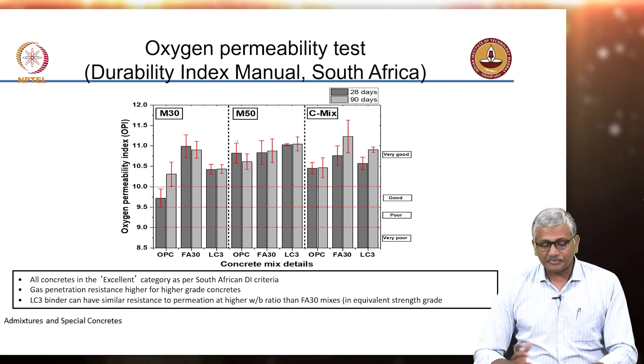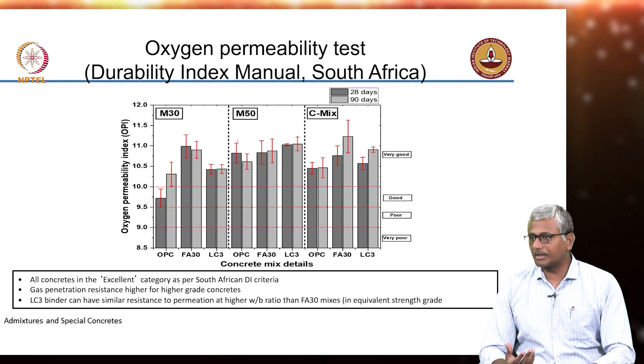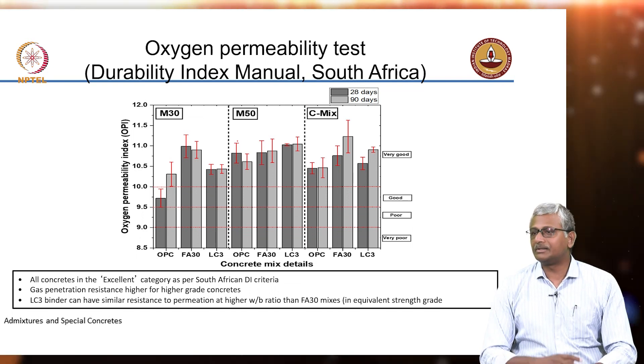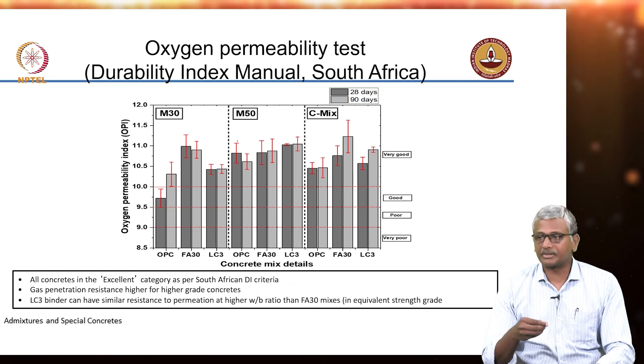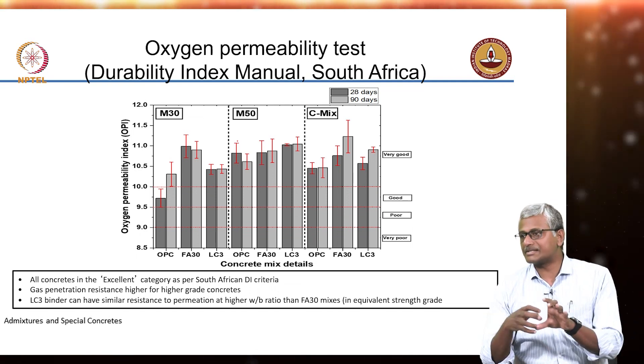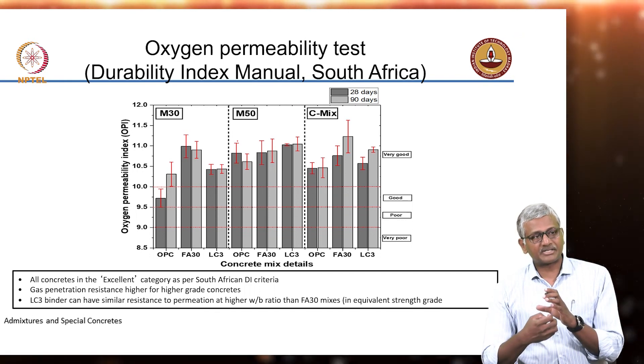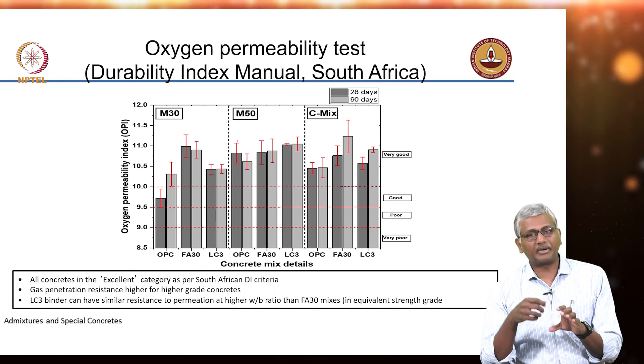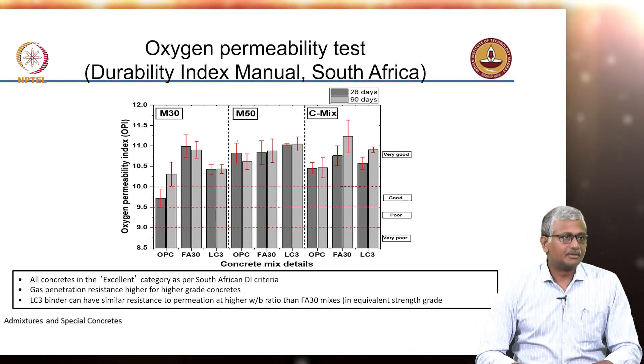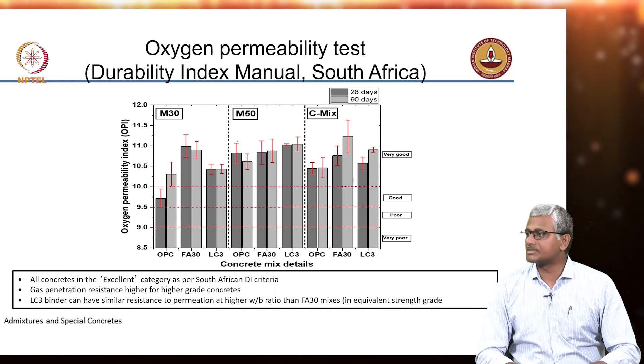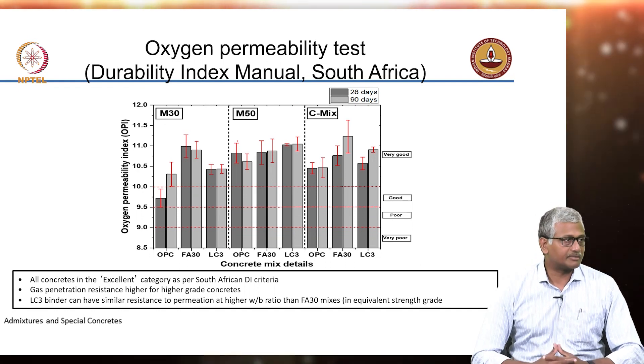In terms of gas permeability, the oxygen permeability test is one of the common tests used to determine the permeation capabilities of a gas through a concrete system. The idea is that you pressurize gas on one side of the concrete and look at the passage of gas through it by monitoring the decrease in pressure on the applied side, which is directly related to the permeability of the concrete. More permeable concrete means the pressure will decrease faster.